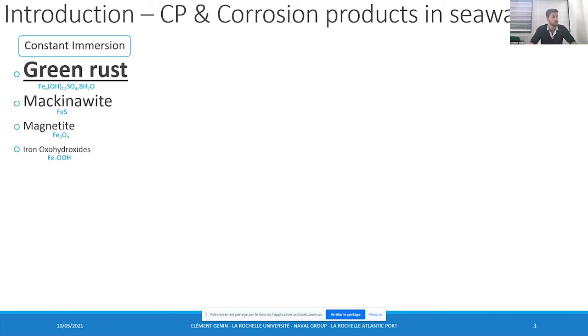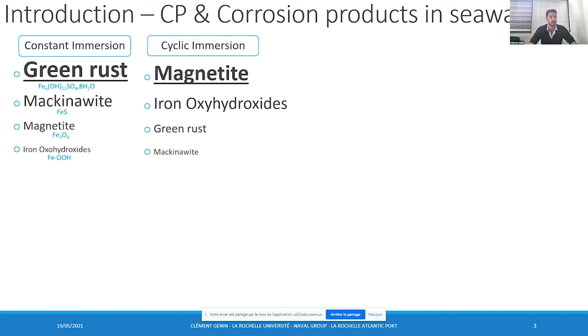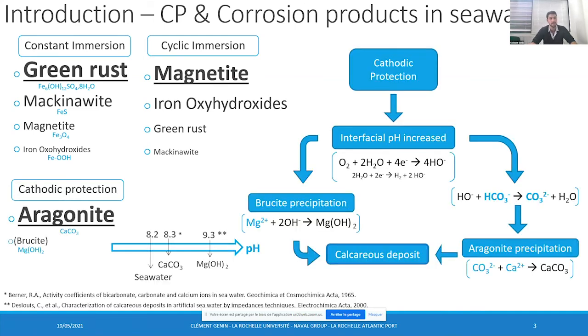Okay, so to better understand the phenomena involved in the tidal zone under cathodic protection, it's important to have an overview of the corrosion phenomena that occur in this area. First of all, constant immersion mainly produces green rusts, while cyclic immersion enhances the production of magnetite. Cathodic protection, on the other hand, implies an increase in interfacial pH, which leads to the precipitation of aragonite, calcium carbonate. Brucite could precipitate with a pH higher than 9.3 and lower cathodic potential, which are rarely achieved through galvanic cathodic protection.